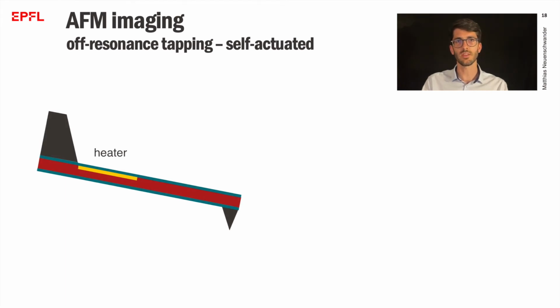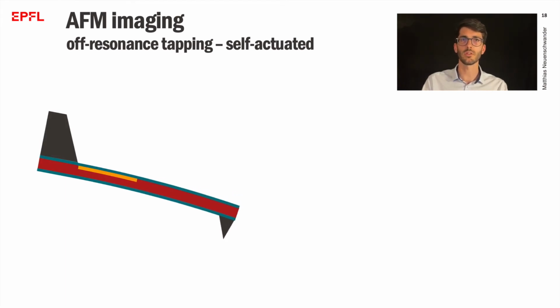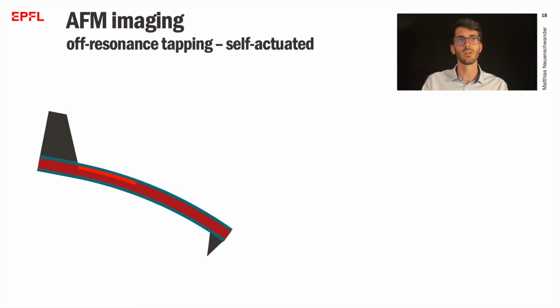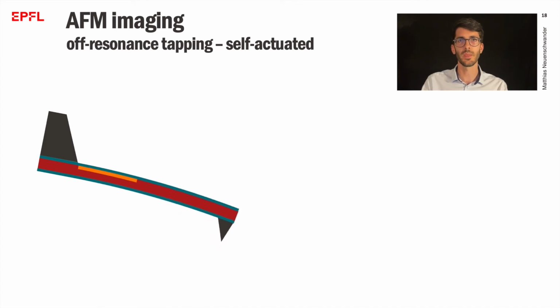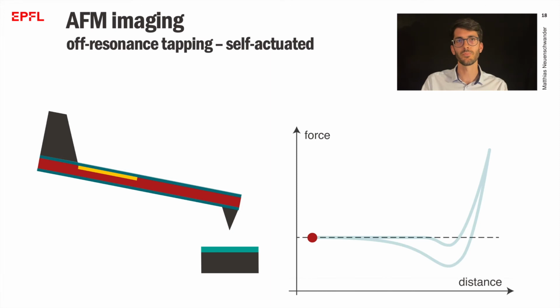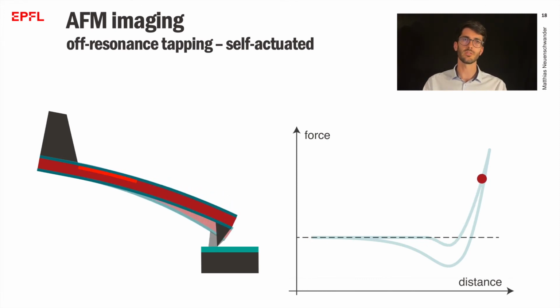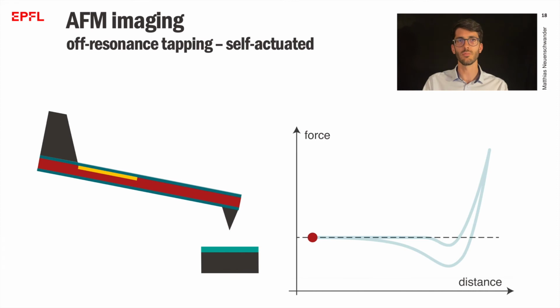The operation looks like this. A sinusoidal current flows through the heater, modulating its temperature and bending the cantilever down and back up. This free motion is recorded. We call it the background. In the presence of a sample, the cantilever will stop as soon as it touches the surface. The force curve is then obtained by subtracting the background from the actual measured motion.